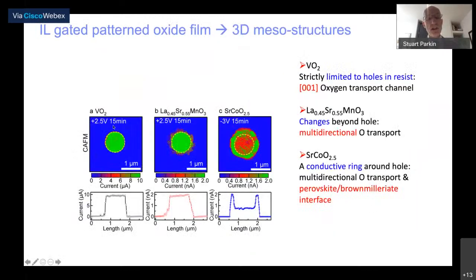Now we do this by gating through holes. These are micron-sized holes in a resist layer. After we remove the resist, we carry out conducting atomic force microscopy. On vanadium dioxide, the region in the hole in the resist layer is converted to a metal, and we see conductivity. The same applies for lanthanum strontium manganese oxide and strontium cobalt oxide 2.5.